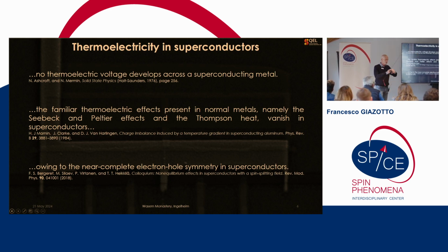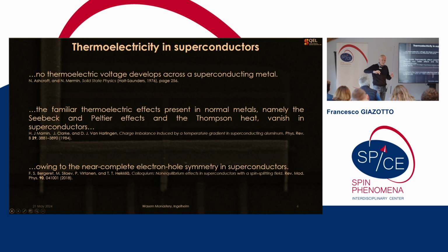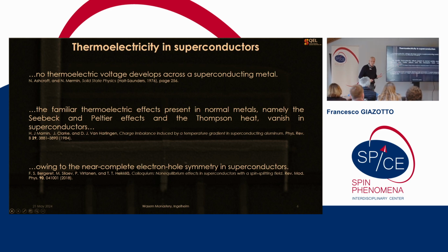If you apply a thermal gradient to a bar of superconductor, the quasi-particles will react according to the response of the dissipative fluid in the system, and the system will be shunted by the motion of supercurrent, so thermoelectricity will appear as a thermophase in a superconductor. The thermophase is basically the demonstration of thermoelectric response in superconductivity. But the thermophase is not something good to produce power.